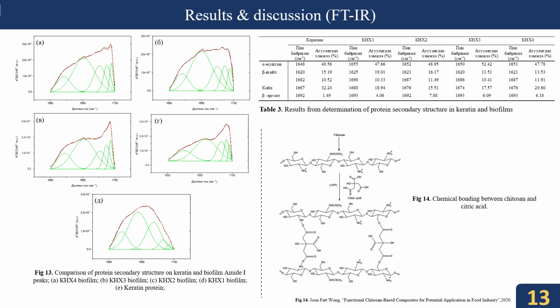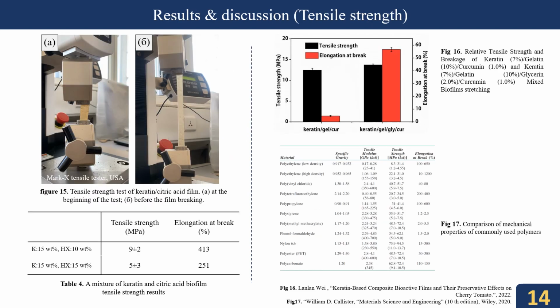The greater the proportion of alpha helix in the protein, the stronger it becomes, the more resistant to mechanical action and the more flexible it becomes. Then tensile strength analysis was performed using the appropriate content of the biofilm formations. For example, 15% keratin with 10% citric acid, and 15% keratin with 15% citric acid biofilms. The other biofilms were not included in the tensile strength test because they were too liquid or too hard to break.